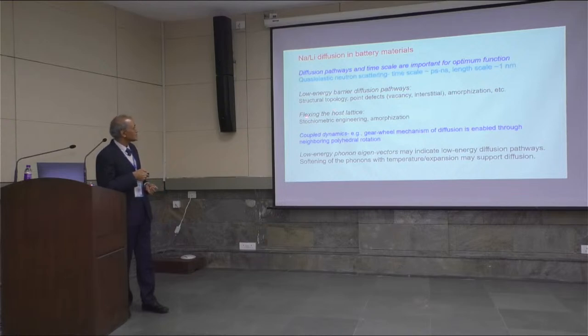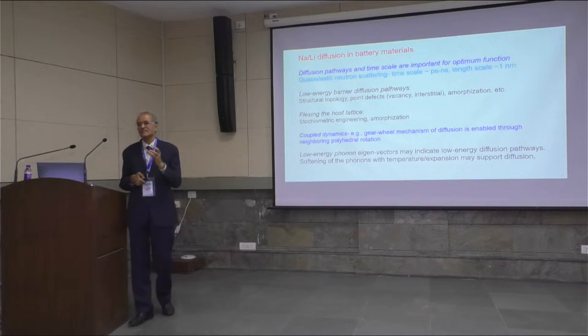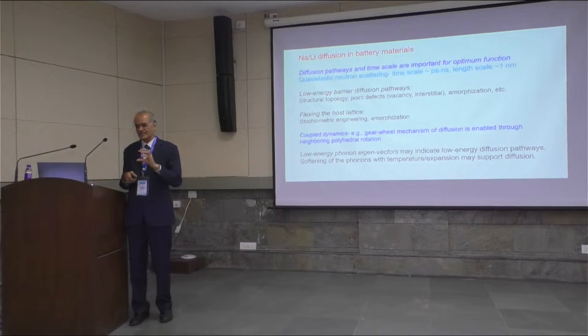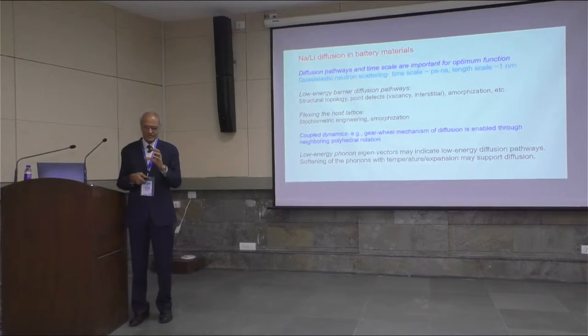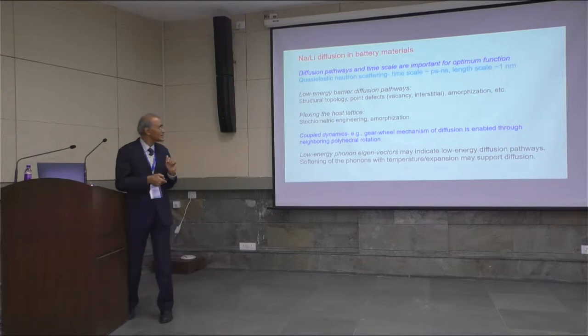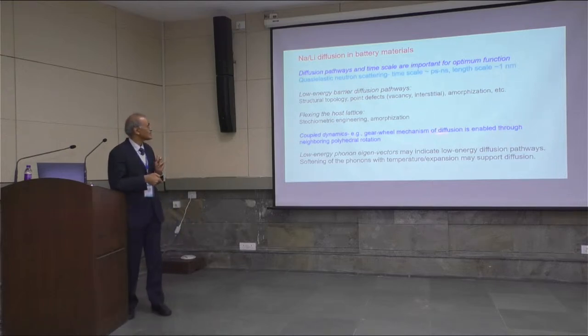Then the other aspect is whether you can flex the host crystalline lattice by some stoichiometric engineering or traditional methods. Then a couple of things that we found is that in certain materials, if you have polyhedral groups like SiO4, for example lithium sulfate or lithium phosphate, a polyhedral group of atoms like PO4 or SO4, its rotation is coupled with the translation of the lithium atom. And so that is called a gear wheel mechanism.